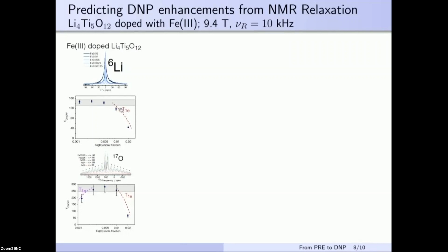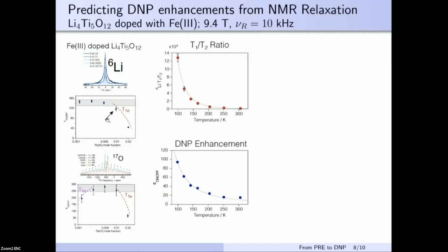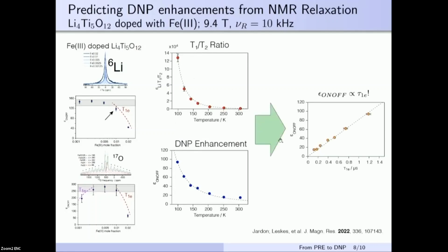Now we wanted to see if we can say something more quantitative about this change in T1e using the T1 over T2 ratio that I showed in the first part of the talk. For that, we took one of these samples and looked at the lithium-6 enhancement as a function of the temperature from 100 Kelvin all the way up to room temperature. At the same time, at each point, we were measuring the T1 and the T2 relaxation times. If we take the equation to get the T1e from this ratio, we actually observe a linear dependence of the DNP enhancement with this electron relaxation time.